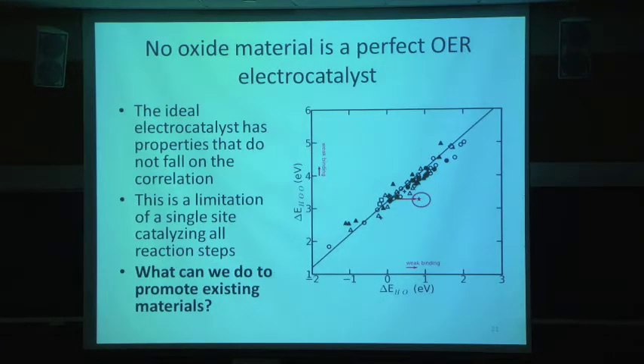So where would that perfect material lie? Here again, I show the correlation between step 2 and step 3. This star indicates where you'd have to be on that 0 millivolt overpotential. And you can see it sort of sits way off the correlation. There are no materials in what we screened that fall over here. Now, that doesn't mean there's not a material. It just certainly means we didn't find one in the fairly comprehensive screening that we did.